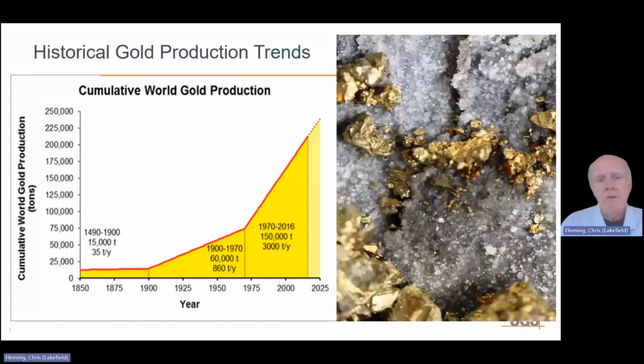I believe an average over this next 60 or 70 year period of the feed grade to a mine would have been in the 5 to 10 gram per ton range. And in that period, another 60,000 tons of gold was added to the above ground inventory for an average of about 860 tons per year. So very dramatic effect that this new technology had on production around the world.